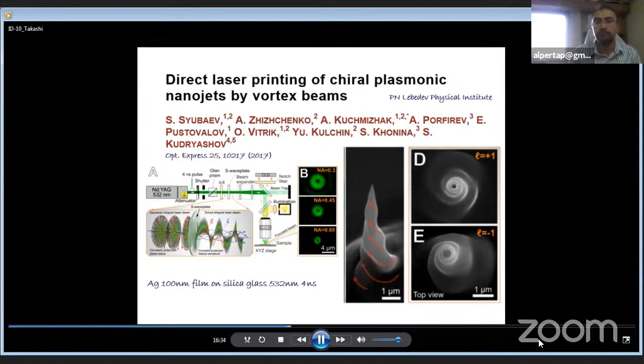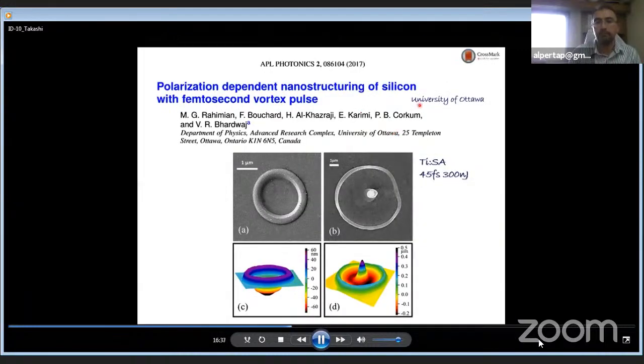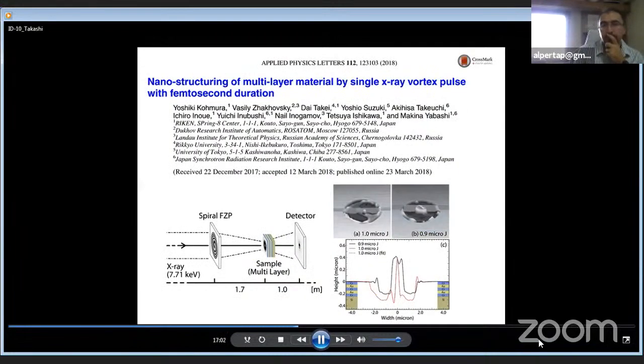And another research group, Ottawa University, can fabricate silicon needles by femtosecond vortex pulse deposition. The structure is quite beautiful, and the surface has no debris at all. This is a femtosecond laser effect. And this is a Japanese group. They fabricate needles on the surface of multilayer material by deposition of a single X-ray vortex pulse with femtosecond pulse duration. It is also quite interesting.